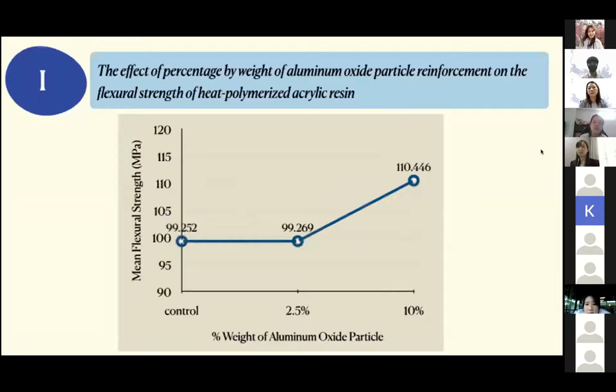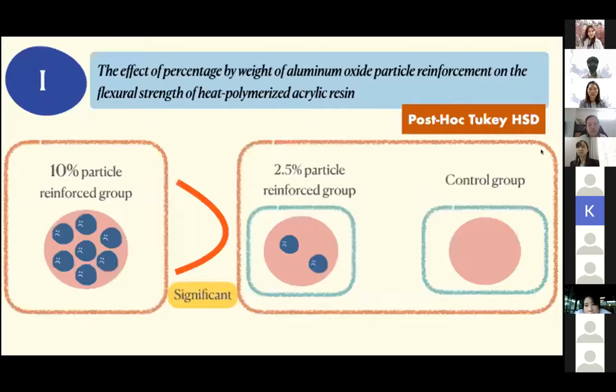This graph demonstrates that mean flexural strength increases as the percent by weight of reinforced alumina increases from control to 2.5 to 10%. To summarize, the mean flexural strength of 10% particle reinforcement is significantly higher than that of the control and 2.5% reinforcement.